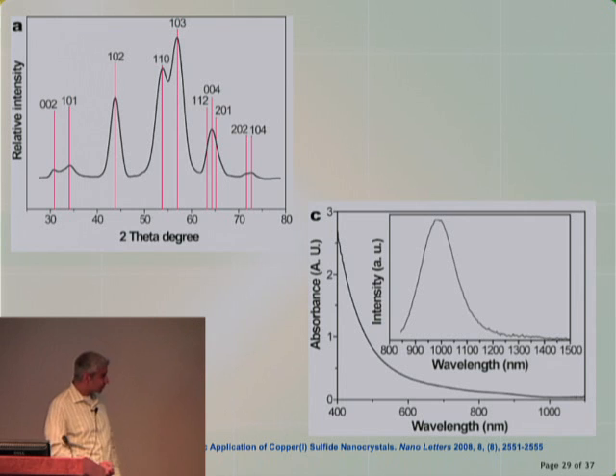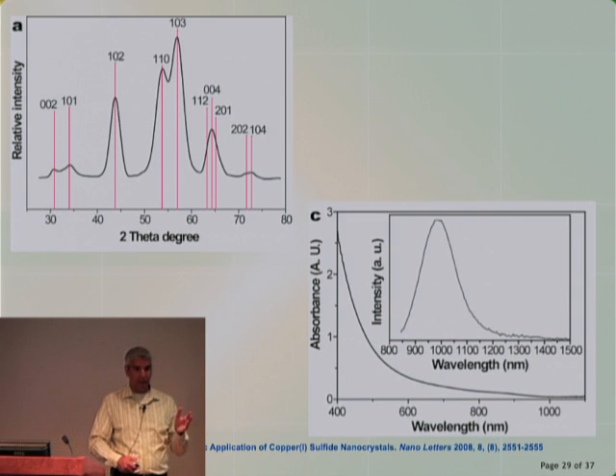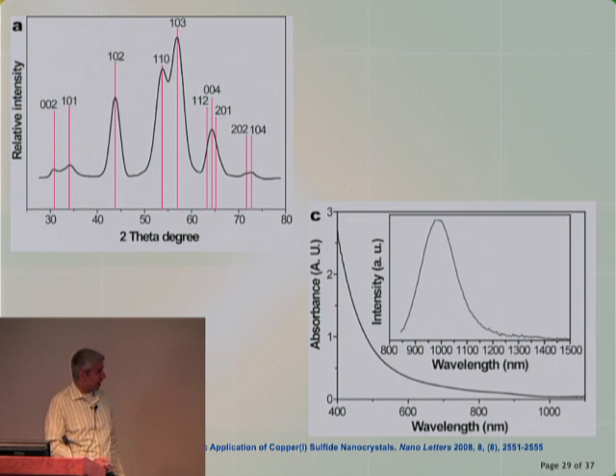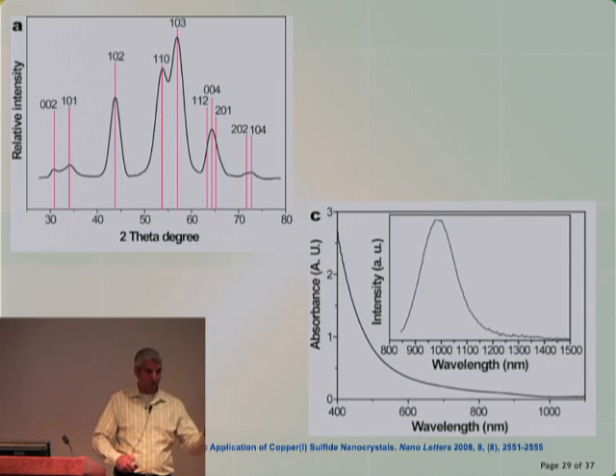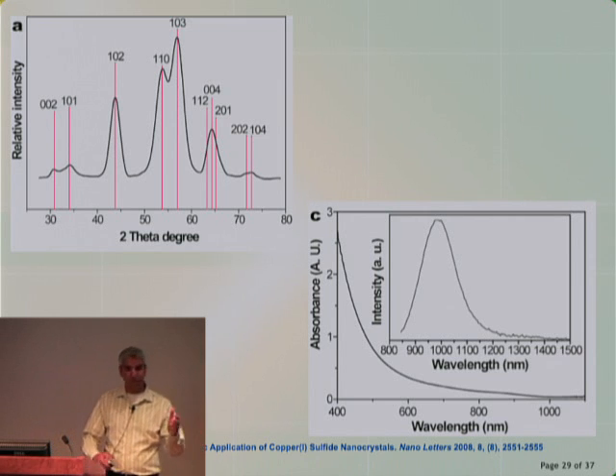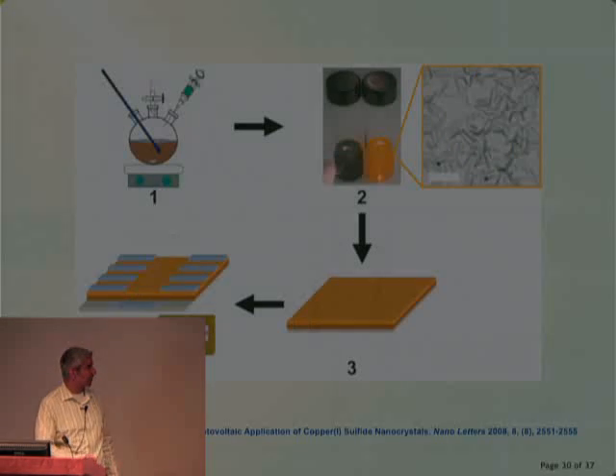This last chart here is called an absorption spectra, where we can try to understand where the band gap is. The copper sulfide has a very traditional indirect band gap feel on the absorption, so it has this long, steady rise. And when we extrapolate where it rises, we see that the band gap is 1.2 to 1.3, which is right in the ballpark of what we would expect.